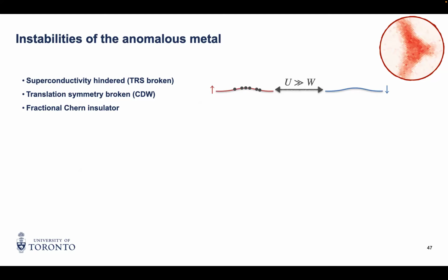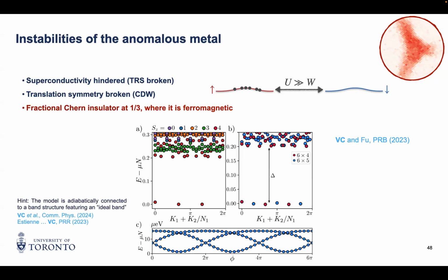And so then you can think of breaking other symmetries and not only charge conservation as the superconductor does. So the other symmetries you can break in the system are translation symmetry, in which case you would form a charge density wave, or just a translation symmetry broken state. The other competing state is a fractional Chern insulator, so the fractional quantum Hall analog that I was discussing above. Just by running the calculation on the specific model we had, we found that at filling fraction 1/3 of that band, so when we fill 1/3 of electron into that band, the system remains ferromagnetic, and this is the one that is favored. But you can also just check that prediction.